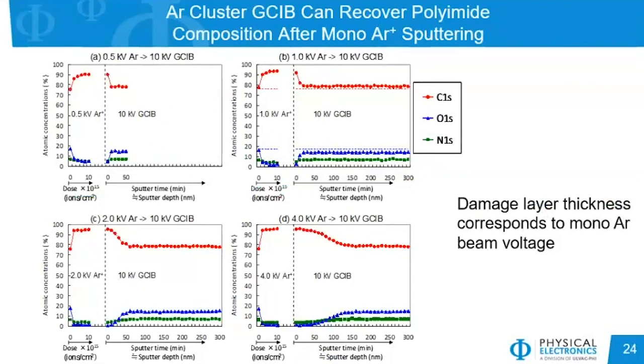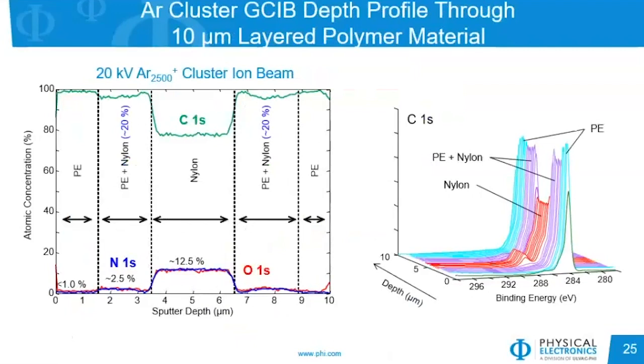In each of these figures, starting from the top left, we have used increasing energy beams of monoatomic argon and then switched over to a 10 kV argon gas cluster beam. And we can see that even though the composition is not what is expected at the beginning of the profile, as we sputter with the GCIB, we eventually reach the expected composition for clean polyimide. And so that allows us to sputter profile through quite large depths of material.